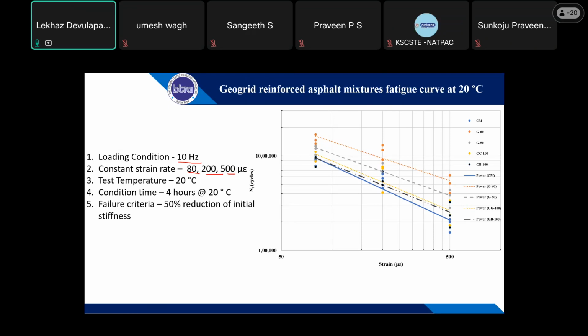stiffness value. And then we have conditioned the specimen at 20-degree temperature for 4 hours, and the whole testing is done at 20-degree. So you can see these are our strain levels. It starts from 80, then 200, and then 500. The number of cycles to failure for the control mix was somewhere around this one, which was nearly 9 lakh cycles, I can say.